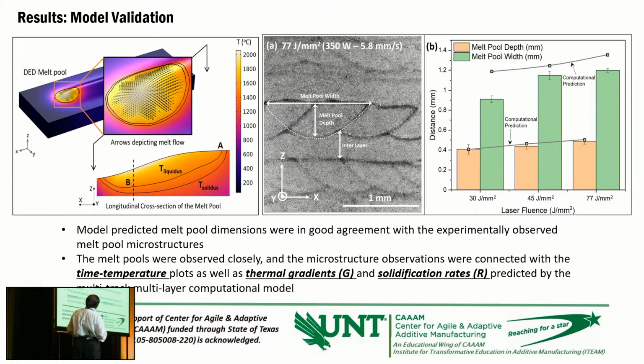In this layer you can see the melt depth. This is an overlap region between the two tracks. So the melt depth and melt width are given here. By those models, we first confirm the accuracy of the model by confirming the prediction of the melt depth and melt width. If it doesn't match, then we tweak the model to match these measurements experimentally. And once it is close enough, then that model is ready to use for the prediction of all other effects in the material. So that is shown here. These are computational predictions, and these are the experimental measurements of depth and width, and so on.